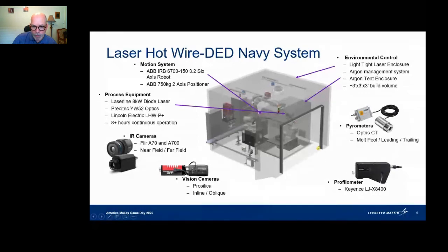And then we've also implemented a profilometer, a Keyence profilometer, so that we can scan the part intermittently during the build. So we'll stop the build at designated layers and scan the part to again provide data back to our models of things such as bead height. We will predict bead height at a specific layer, but then by measuring with the profilometer, we can determine the accuracy of that prediction during the actual build.